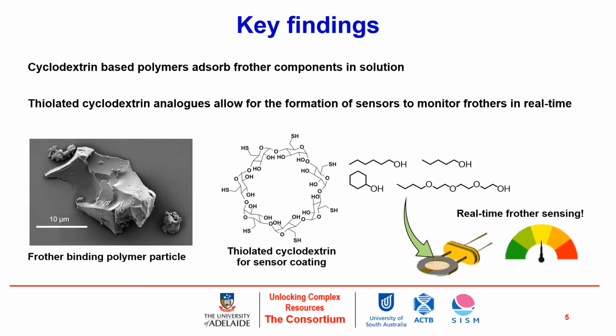Key findings to date have been that cyclodextrin materials can be used to form different structures, be they single molecules or polymers, that interact with these key flotation agents and allow us to develop a platform that is able to selectively interact with them in solution. On the left-hand side of this presentation, I have an example of one of these materials, which I've developed as a polymer and used to validate the binding of cyclodextrins for these materials in solution experiments. In the center, I have a thiolated cyclodextrin that's been developed that has the handles on it necessary to attach to the gold quartz crystal microbalance surface, and this will provide a means of giving that real-time sensing of those flotation agents.